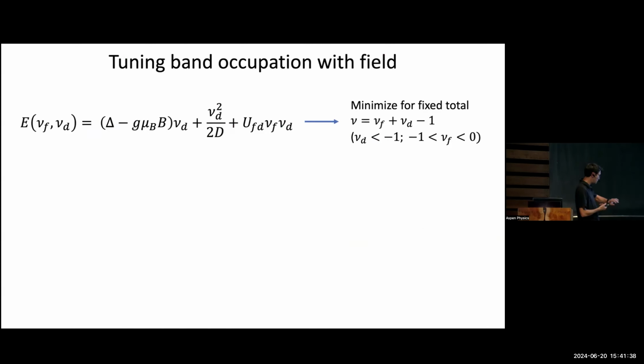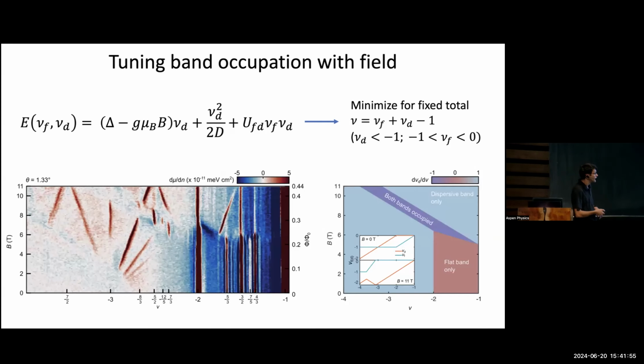We can cook up a very simple picture for the free energy of the system, taking into account the original band offsets, some difference in effective Zeeman field, some kinetic energy associated with the dispersive bands, and some Stoner repulsion between different types of carriers. And if we just minimize this free energy and ask the question, what's favored in the ground state? What you get is a picture that looks like this. So low magnetic field and low filling in this red portion is favorable to occupy the opposite type orbital. So this regime here, you're occupying still the flat band. But eventually, magnetic field is large enough such that it's favorable to occupy a spin-aligned type orbit. And you start to fill these more dispersive bands at high magnetic field. So this is actually a transition from a spin singlet state on a particular site. So it's like a singlet state of a quantum dot to a spin triplet type state, again, with both spins on the same real space site, but occupying now different orbitals.